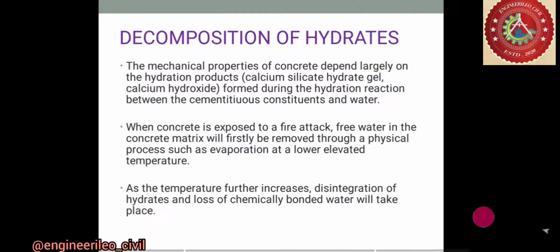As the temperature further increases, disintegration of hydrates and loss of chemically bonded water will take place. The decomposition of calcium hydroxide occurs at about 350 degrees centigrade. Then the partial volatilization of calcium silicate hydrate gel commences at about 500 degrees centigrade. The pore size and porosity of the hydrate matrix will increase, and mechanical properties like strength and elastic modulus of the hydrates will be weakened. Moreover, at 573 degrees centigrade, the crystal structure of quartz in siliceous aggregate transforms from a low temperature phase to a high temperature phase. Such transformation is accompanied by approximately 1% volume increase, which accelerates the disintegration of the hydrates.